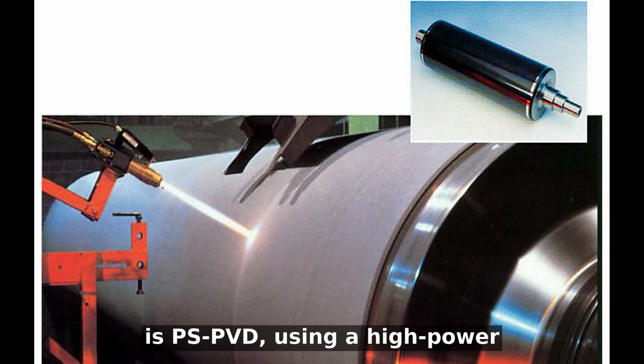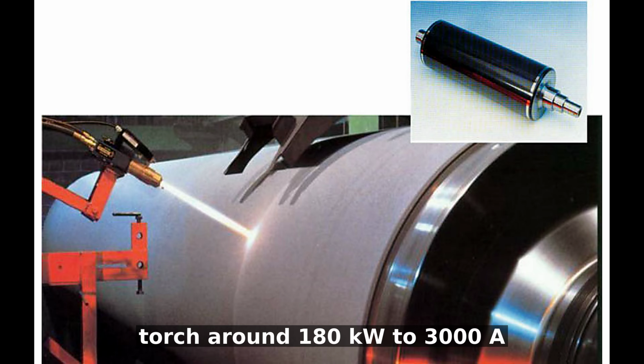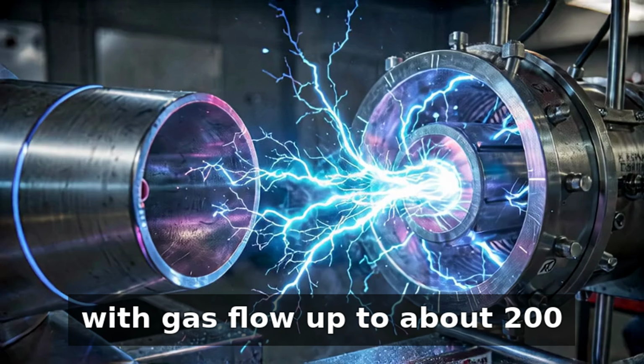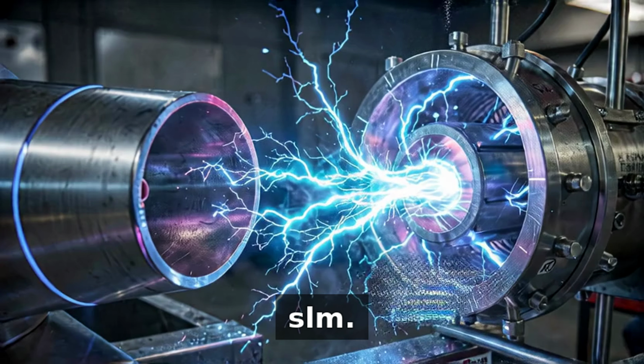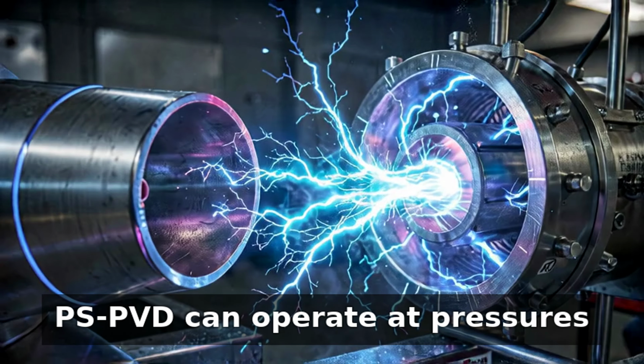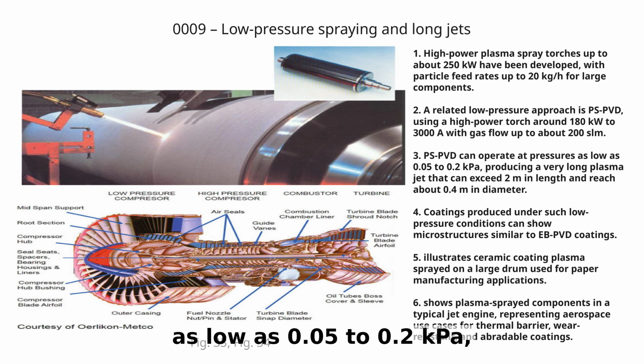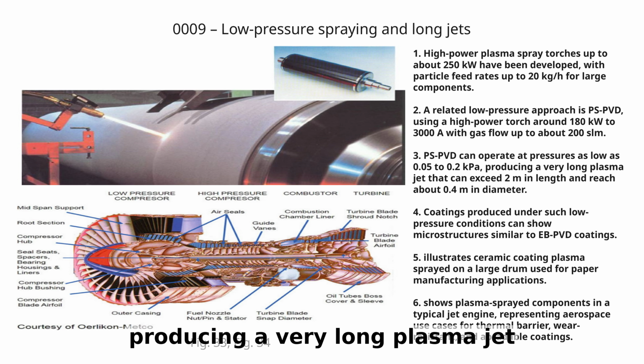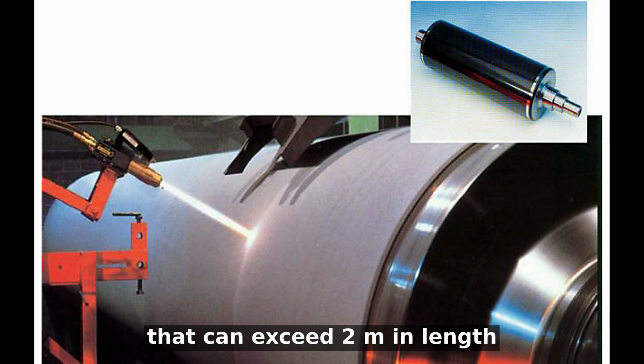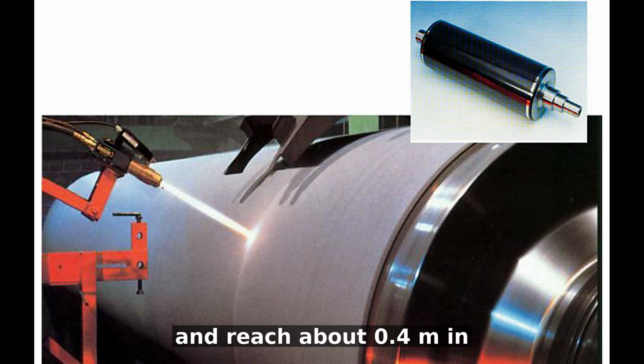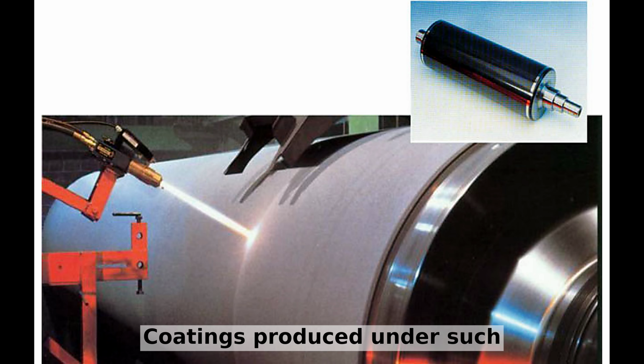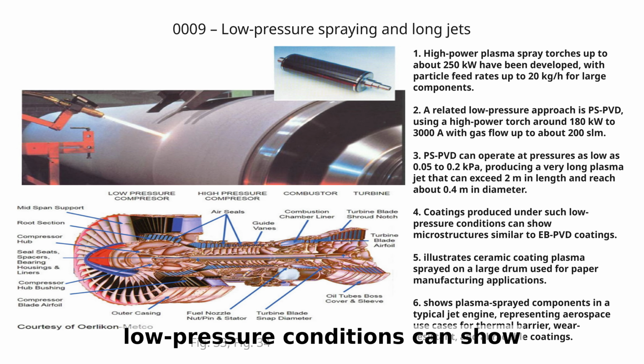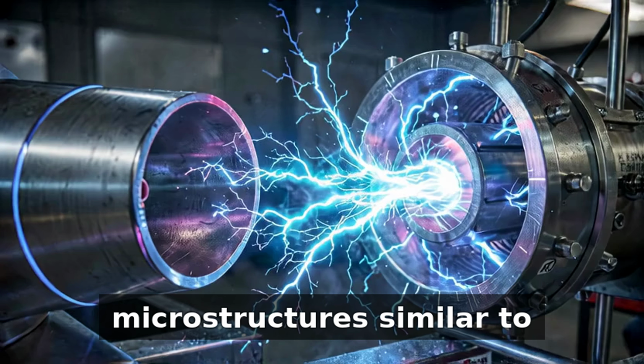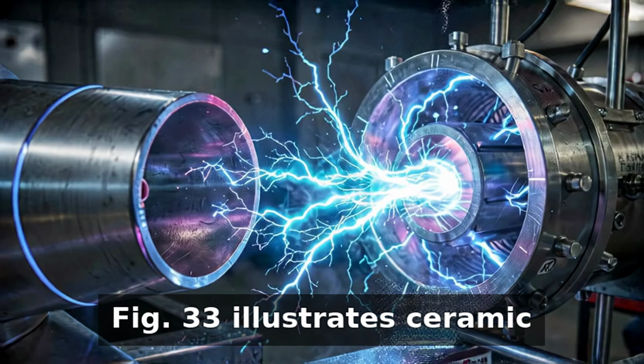A related low-pressure approach is PSPVD, using a high-power torch around 180 kilowatts to 3000 A with gas flow up to about 200 SLM. PSPVD can operate at pressures as low as 0.05 to 0.2 kilopascals, producing a very long plasma jet that can exceed 2 meters in length and reach about 0.4 meters in diameter. Coatings produced under such low-pressure conditions can show microstructures similar to EBPVD coatings.